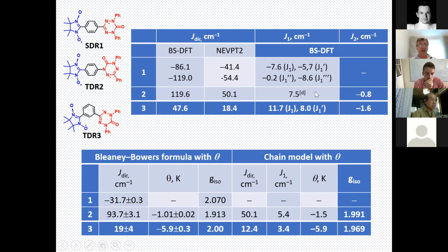Also, we analyzed intermolecular interaction and revealed that in radicals 2 and 3 we also have ferromagnetic exchange interaction. More important, this exchange interaction actually connects the radical molecules into chains. So we applied two models, the Bleaney-Bowers model and chain models, to approximate the chi-T temperature dependence. And the second model, the chain model, is more realistic because we have reasonable inter-radical exchange interaction.